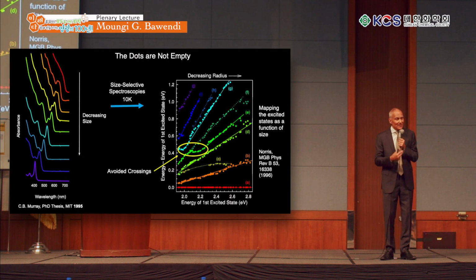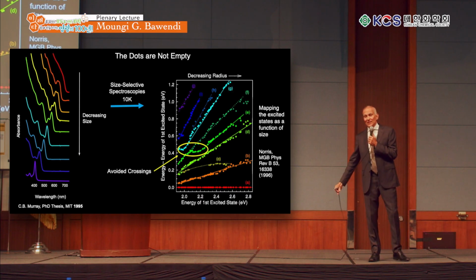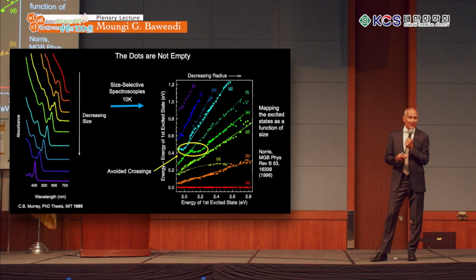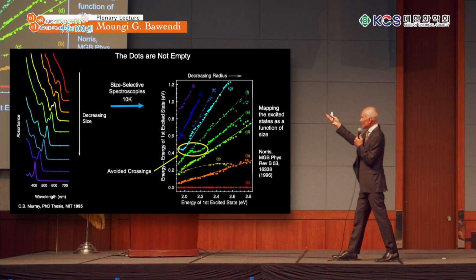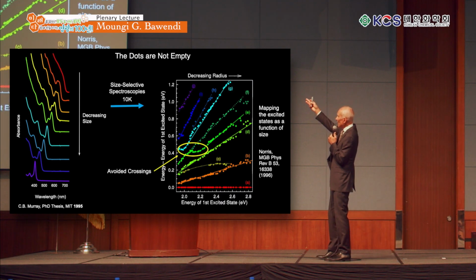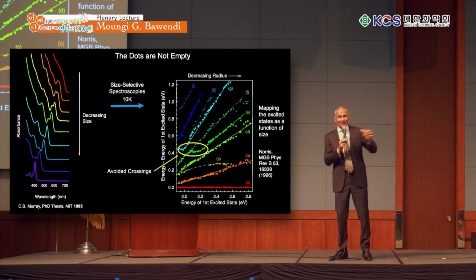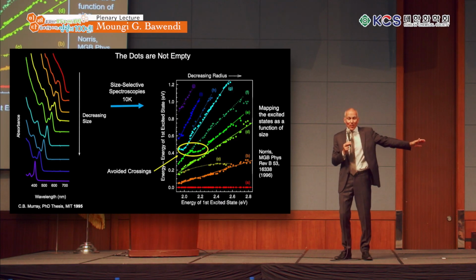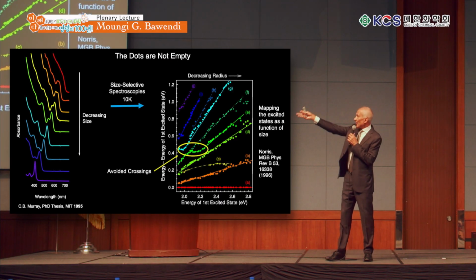So then when we had these beautiful samples, the first thing that we decided to do was to study the physics of them. And one of the things you can do then is to go to low temperature, 4 Kelvin or 10 Kelvin, cryogenic temperatures, and really begin to study how these harmonics depend on the size of the particle. So my x-axis here is basically size. I have it on top. On my left-hand side, your right-hand side, are the small particles, and on the right-hand side, my right-hand side, your left, are the big particles.